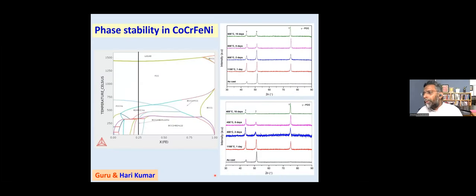Now, the next problem that we talk about is, fine, these alloys I can make, and they can be uniform in composition. But then what are the challenges? The first challenge that comes to me is, I do not know what the phase diagram is for such a multi-component alloy. If you have ever seen phase diagrams, typically we know phase diagrams of binary systems, A, B. To some extent, we know ternary. The moment you cross three elements, there are no phase diagrams available for a four-component system, or a five-component system, or a six-component system. So I do not know what phase can be stable at what temperature, at what composition.